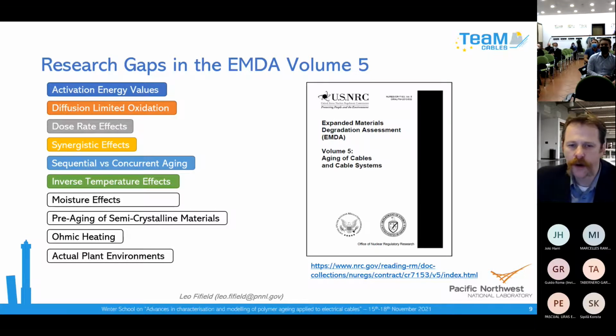Some we know about have problems, but in general, 60 years is fine. But when they went back to renew their license to 80 years instead of 60 years, the NRC wanted a closer look. And so one of those closer looks is at what assumptions were used during that qualification process. You know, many assumptions were used, such as we do some accelerated aging in the laboratory, and it represents what happens over 40 years in the plant. Okay, that's a big assumption.